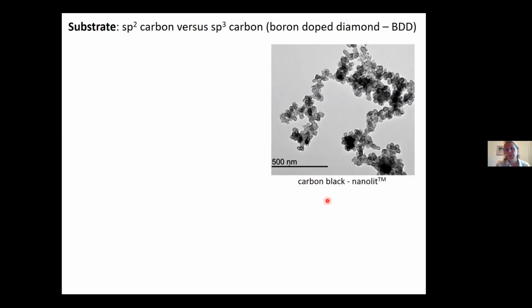So if you look at catalysts and support materials that are used today, traditionally you're going to be looking at sp2 bonded carbon. Most of the catalysts, if we're looking at nanoparticles, are placed on top of this material. The reason is that sp2 carbons do have fairly low background currents, but the biggest probable advantage is their low cost, and they can be made in very high volume. For fuel cell chemistry, you're looking at needing to produce tons of this. However, there are some potential problems of using sp2 carbons, well documented in the literature, which is things like carbon corrosion when you go to elevated temperatures, and then you start to get loss of catalyst material.